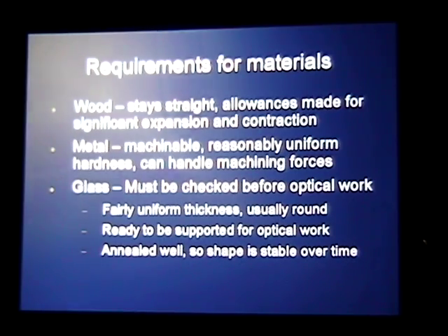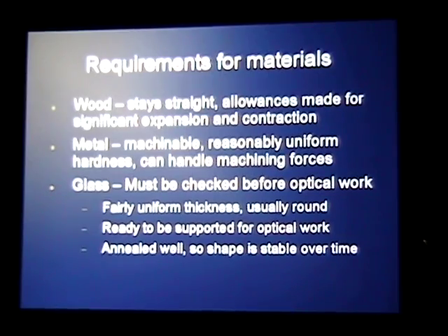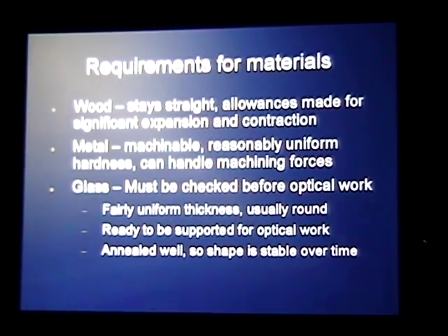It can change shape. And the anneal quality of metal for high quality machining, as well as the glass for high quality telescopes, is of the utmost importance, because what's the use if we polish a mirror to 100th wave and then it changes shape on us? That's bad. So we want to make sure there's very little strain, which you can sort of imagine as a spring within the glass. And if something happens, that spring can release its strain and change the shape of the material.